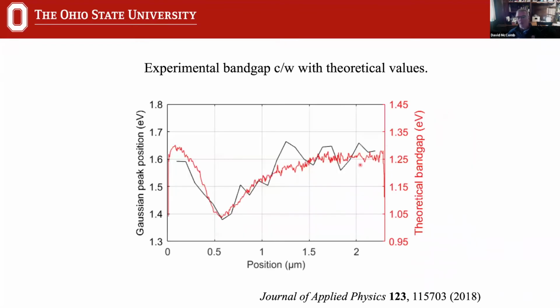And if we overplot that with what we would think the theoretical band gap is based on the composition, we can see that it actually maps extremely well. And so we found a robust way to measure that effective band gap over a large area in an automated fashion. And as we get even better with our zero loss peak, we are now looking at how we can improve that further and whether we can actually get an absolute value of that gap.